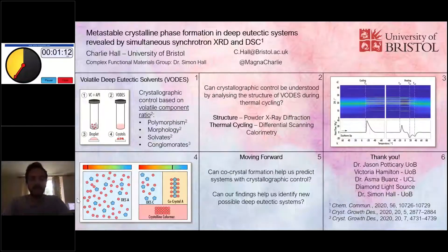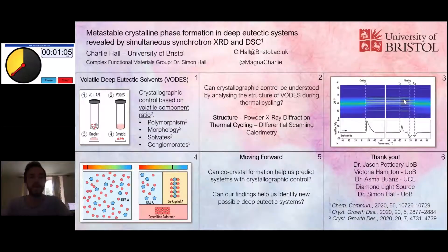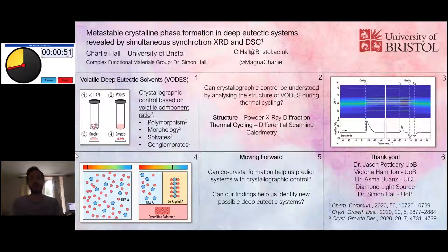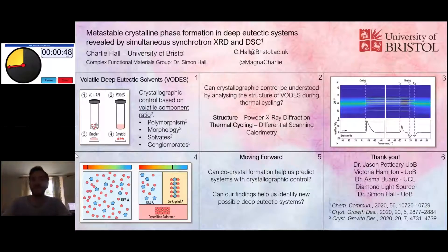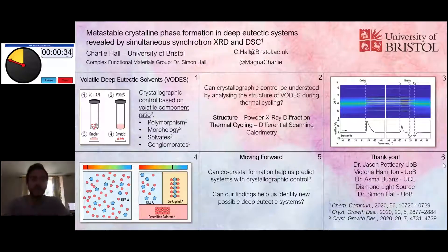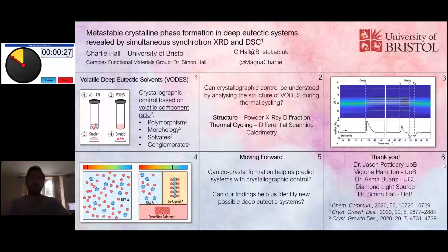What we found is that we get a hierarchy of crystal structures that crystallize out as we cool down the system. First, we tend to get our volatile component crystallize out, but then we see co-crystals of the volatile component and the component of interest. We think these co-crystals are mediating the crystallographic control that we observe in our systems. We also think this might be useful for understanding why deep eutectic systems form in the first place.